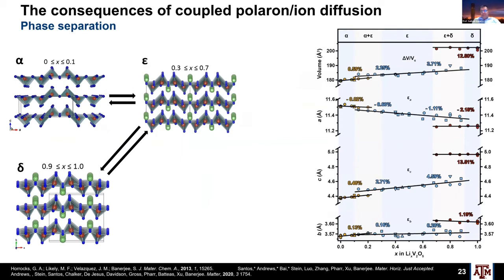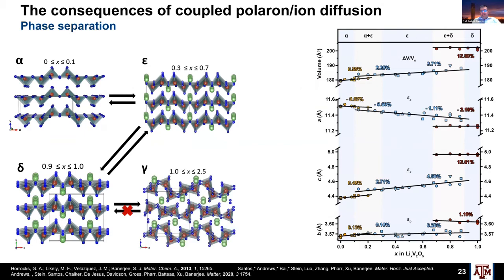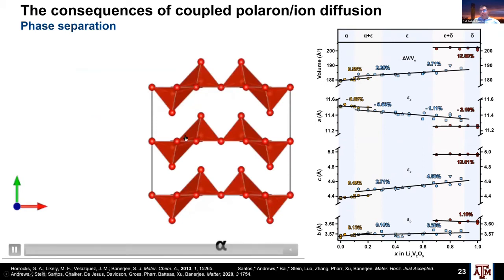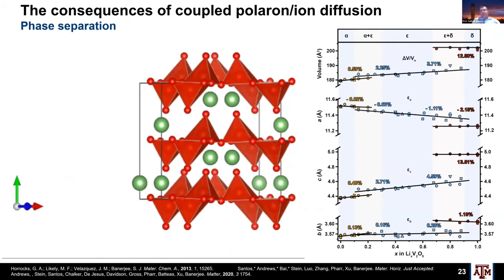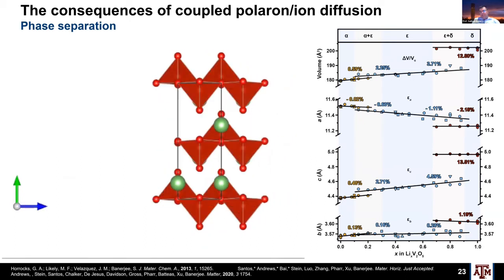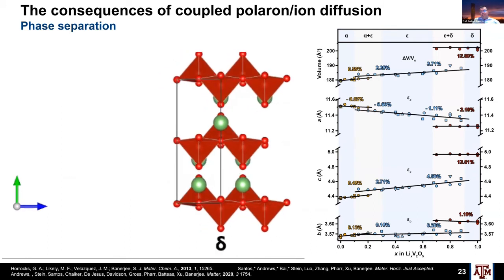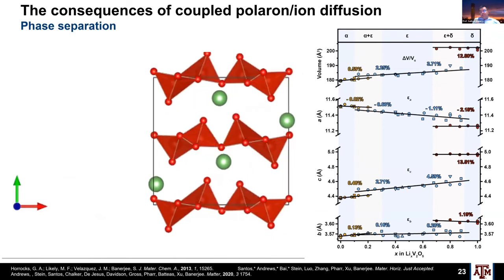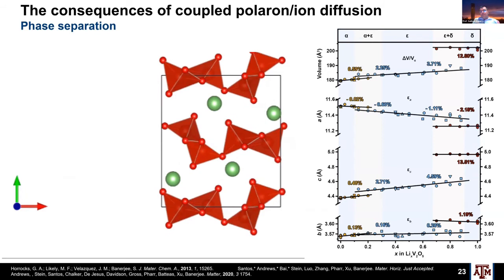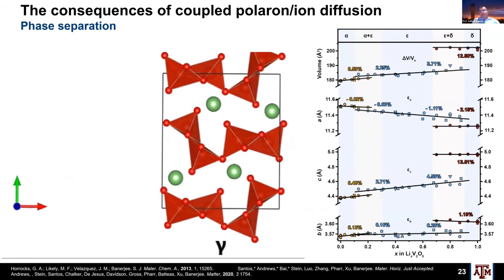So lithium ions are coming in, and as they come in, there's a whole bunch of distortions that happen, and these distortions essentially will result in the lattice changing quite profoundly. Okay, and so you can see here with more and more ions coming in, initially the layers get pried apart a bit, the layers get puckered, and ultimately there's some pretty large changes that are irreversible. So it never goes back. So this is once it goes into this highly distorted gamma phase, right? So this is pretty important.